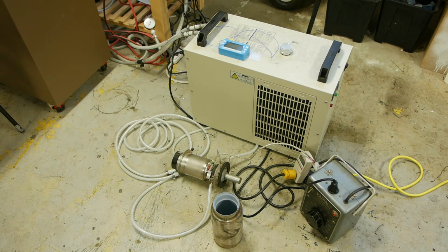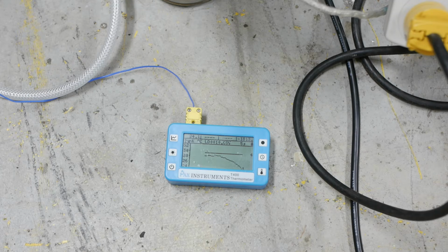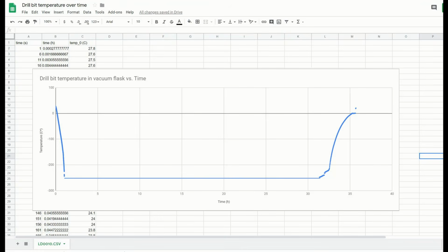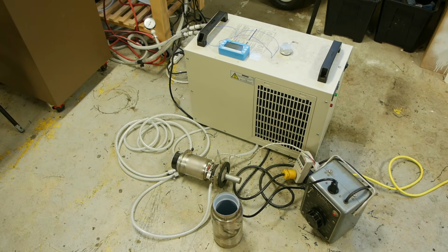And I'm using this PAX Instruments thermal logger, which works really well, except at liquid nitrogen temperatures. It reads a little low. So you can see on the graph here that my cool down period was about an hour, and that's correct. But the ultimate temperature couldn't possibly have been negative 240, because that's much colder than liquid nitrogen. It should have been about negative 200. But anyway, it shows the ramp down and the ramp up that's realistic.